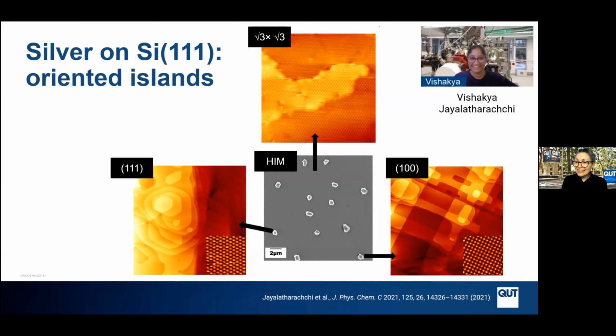Of course, silicon is intrinsically way too reactive to do any sort of molecular self-assembly or even covalent bonding work, simply because molecules tend to fall apart and bond to the silicon substrate very quickly. We get a lot of dissociative adsorption going on on this highly reactive surface. So Vishakya was working to reduce the reactivity of the silicon by terminating it with a silver monolayer, creating a root 3 by root 3 reconstruction, which you see at the top of the slide here. It turned out not to be great for our molecular reaction experiments, but what she did find was that if she increased the coverage of silver, she was able to grow tiny micro islands on the surface that turned out to be themselves very small single crystals.